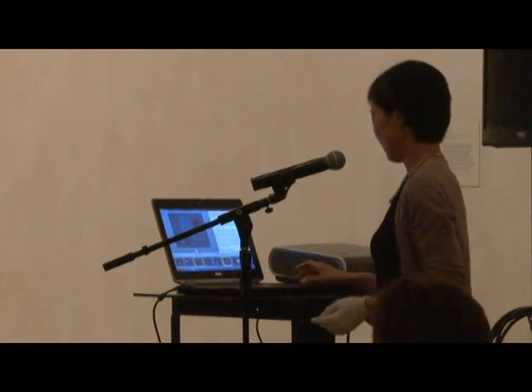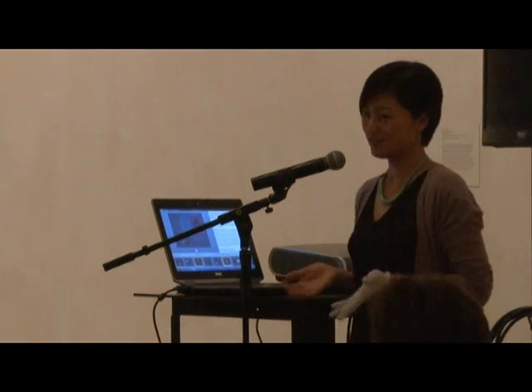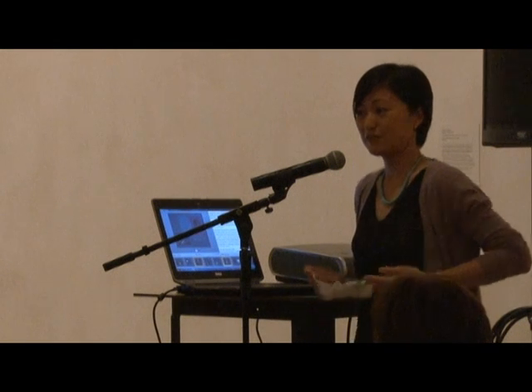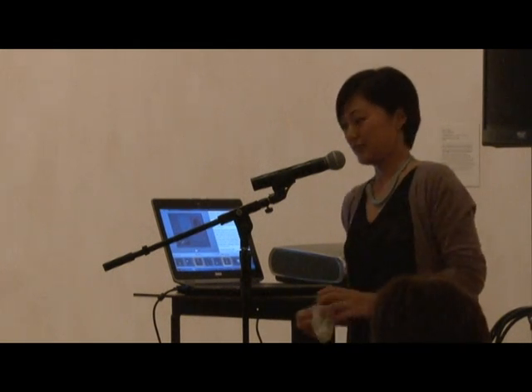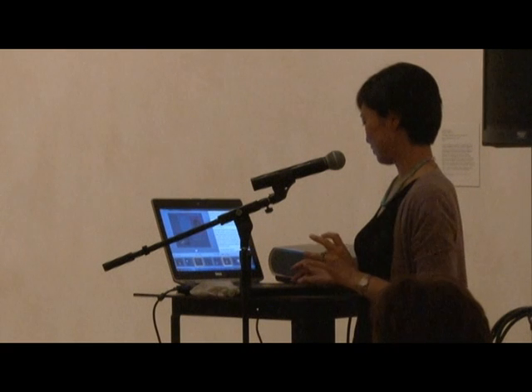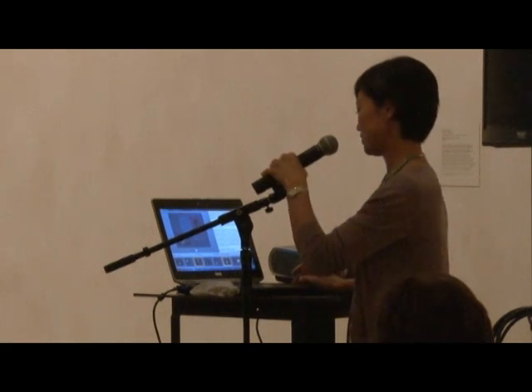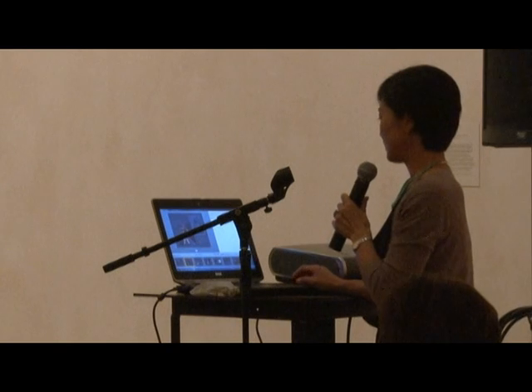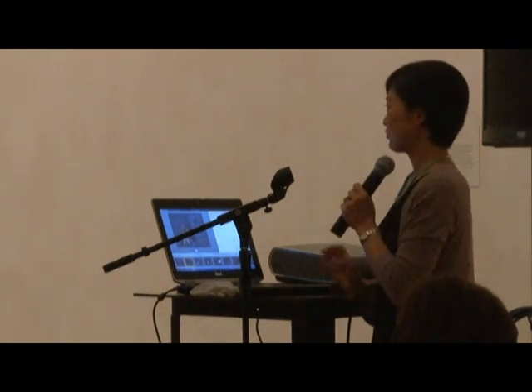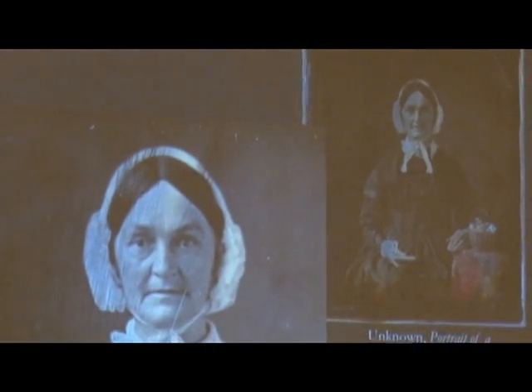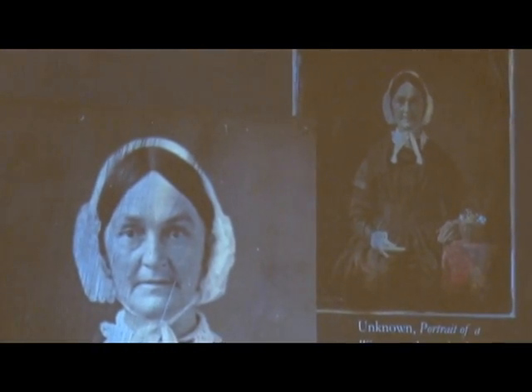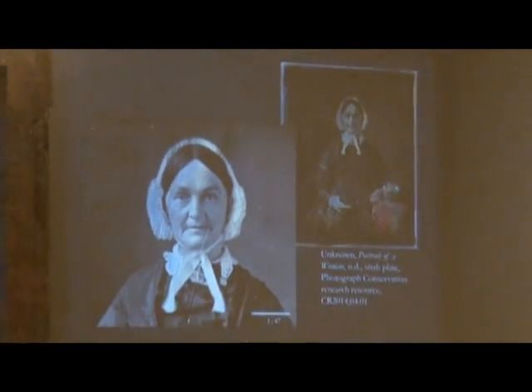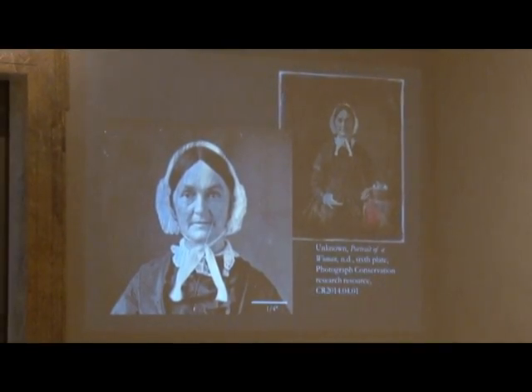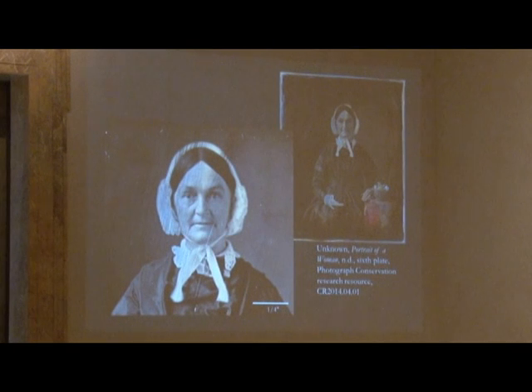Well-processed and well-stored daguerreotypes are chemically very stable, but they're really fragile, susceptible to physical force. And this is an unfortunate example. Even the slightest sweep with a really soft brush can leave these marks, like you can see in the close-up image. Once this damage happens, unfortunately, there's nothing I can do to remedy this condition.